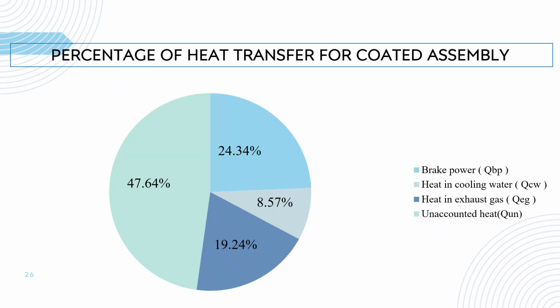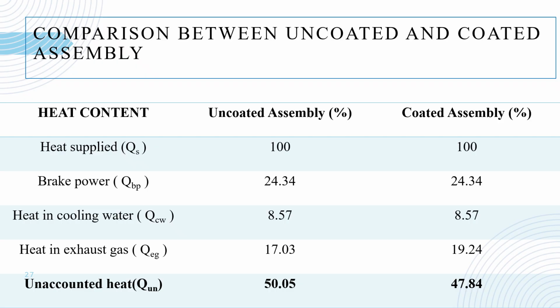The reason being, YSZ has very low thermal conductivity, so it blocks the heat from flowing into the metal components and cooling system. This means that more heat stays inside the combustion chamber and less heat escapes into the cylinder walls, piston, coolant, and lubricating oil. So the combustion chamber remains hotter for a longer duration of time. That's why the amount of heat in the exhaust gas is more as compared to the uncoated one. So this is the comparison between the coated and the uncoated assemblies.